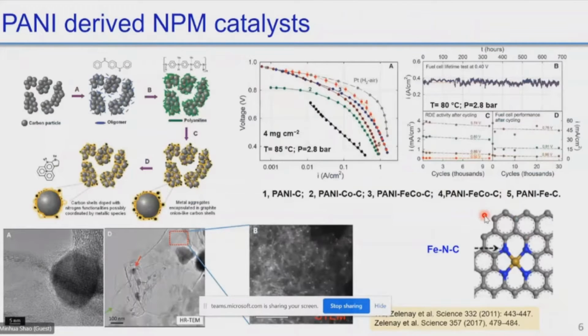Another area for fuel cell cathode development is non-precious metal. A long time ago, people found that some transition metals coordinated with nitrogen and carbon have some activity for oxygen reduction, but this molecule is actually not stable. So recently, they found that if we start with a carbon black support, introduce some iron and nitrogen precursor, and do heat treatment, you basically modify the carbon support and have a thin layer of carbon, nitrogen and iron. This is actually quite active for oxygen reduction.